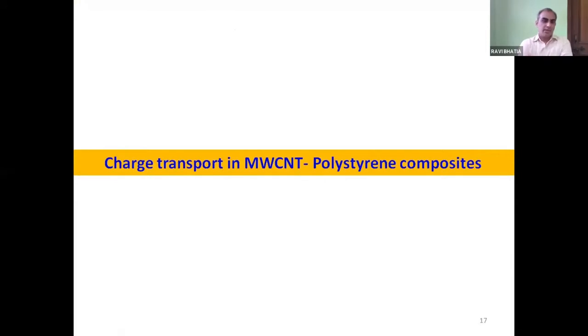So let us now just shift to the charge transport in composites. Composites can be prepared by many techniques. For example, you have a polymer solution, you make a dispersive solution of CNT, mix them together, go for some ultrasonication. Ultrasonication can be the best way to disperse carbon nanotubes in a polymer.